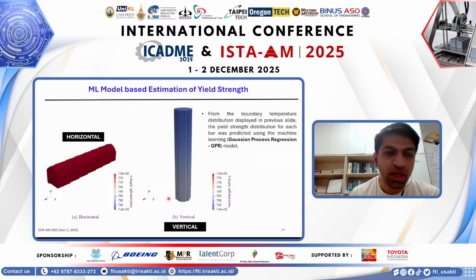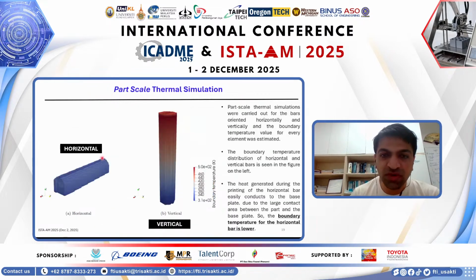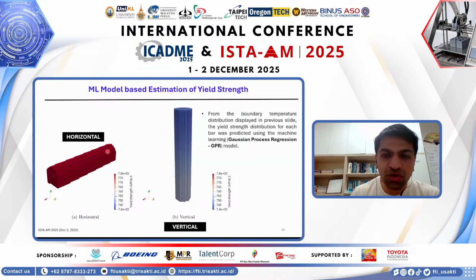Sure. Thanks. And then, these results that we have of the thermal map of the horizontal and vertical bars are then extrapolated to look at the yield strength distribution of the horizontal and vertical bar. While they look the same in color, you can see there's a small variation in the blue color here. So the yield strength of an element in the higher end of the cylindrical bar is not the same as the one in the lower end. It is actually different. So the higher end of the bars have a lower yield strength compared to the lower end of the vertical bar.